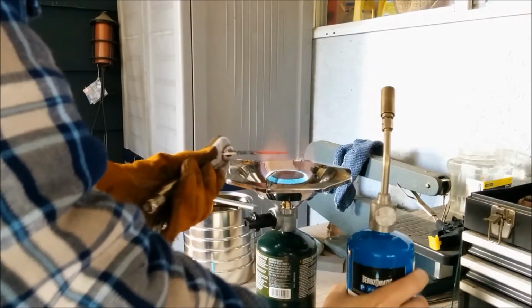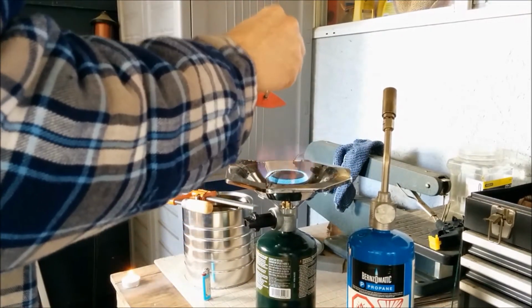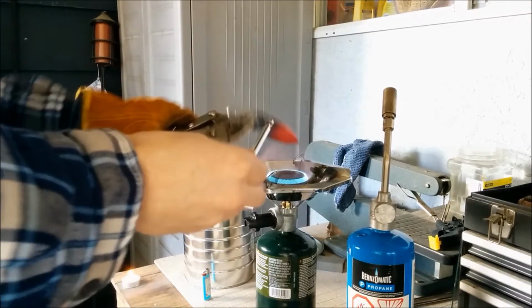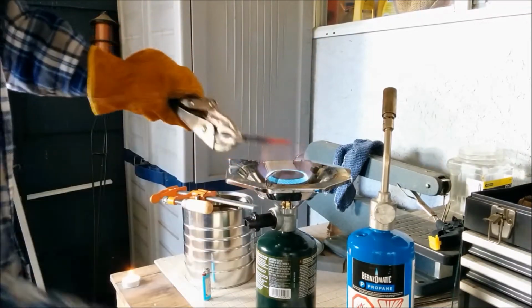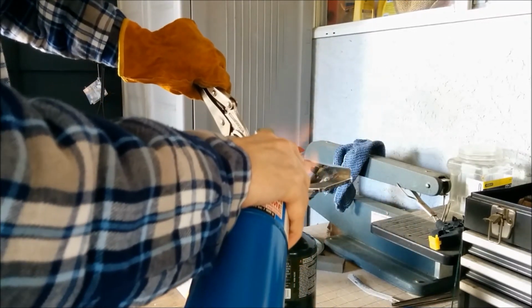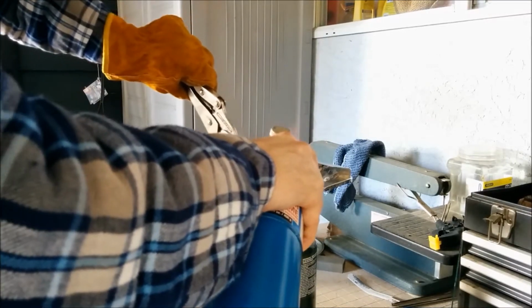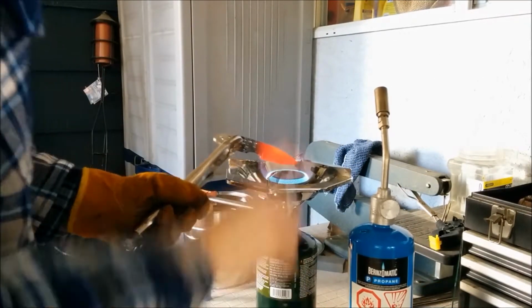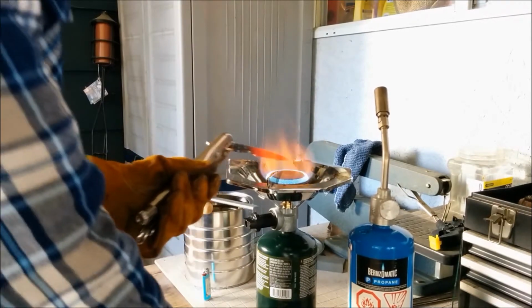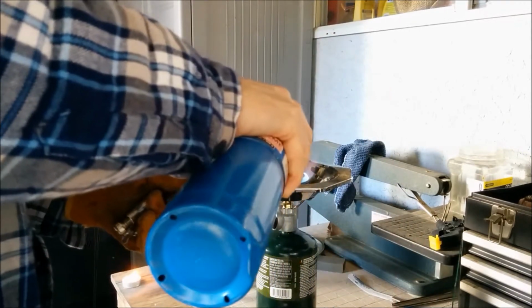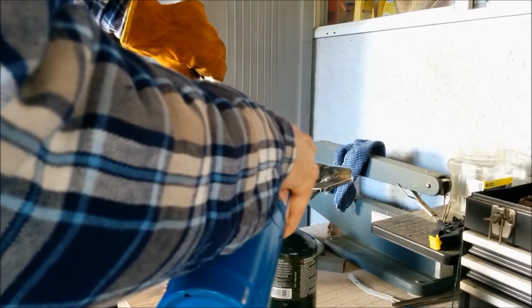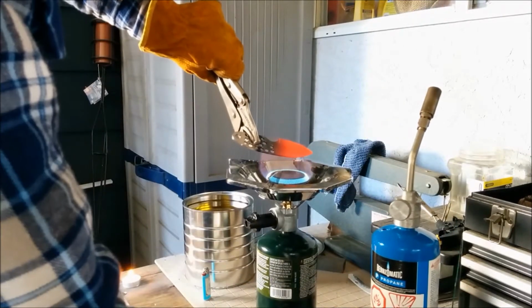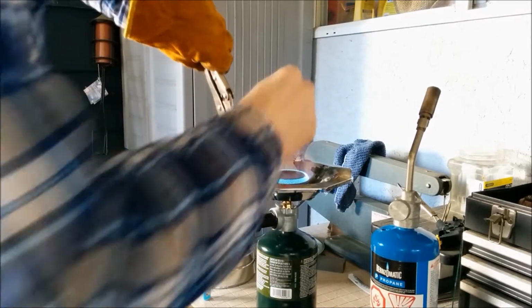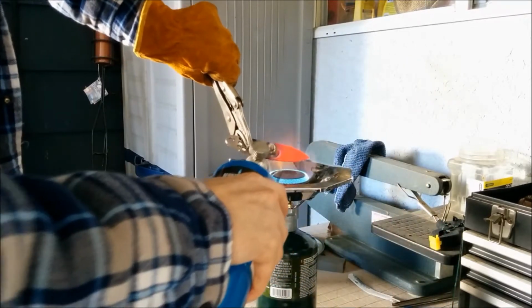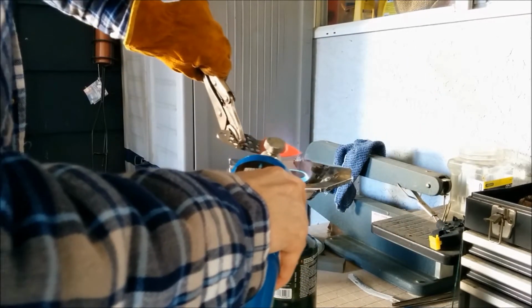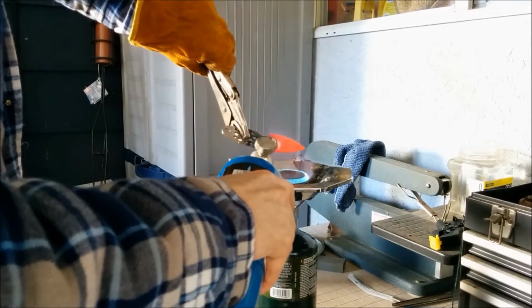You don't want to overheat your edge, so I was trying to direct the heat flow towards the spine. Here I'm checking if it's non-magnetic. I think it's still magnetic there, so I got to keep heating it up even though it's starting to get that cherry red color. So here we go again, checking not magnetic. So now I'm going to heat it up a little bit more, and then I'm going to go right into the quench oil. And just checking to make sure I'm past that point still, and still going to heat it up a few shades more. And then we're going to go as quickly as we can into the quench oil.